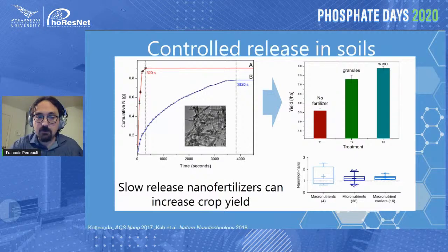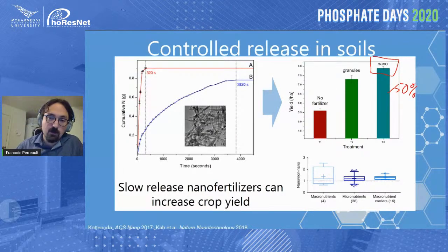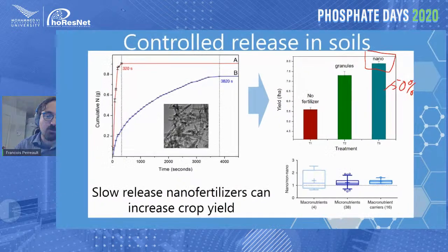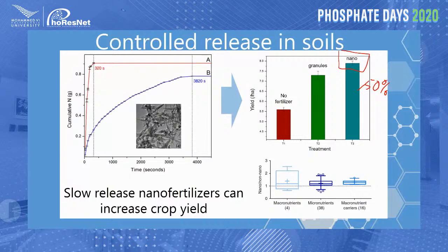And you can see here an example on the left. This is a urea-based hydroxyapatite fertilizer, and by engineering a nanostructure in that urea-based fertilizer, they were able to extend the lifetime of release by more than an order of magnitude. So you have a much lower release of urea. And then the more important information is that when they applied this to a field to evaluate, is this nano fertilizer really better? They saw an improvement in crop yield for the nano fertilizer compared to the granular commercial fertilizer. And this is something that is not indicated on the graph, but they saw this at essentially 50% of the dose of the granular fertilizer. So half of the fertilizer was used, but they achieved higher performance, which really shows the capacity of slow release compounds in enhancing plant growth on the field.